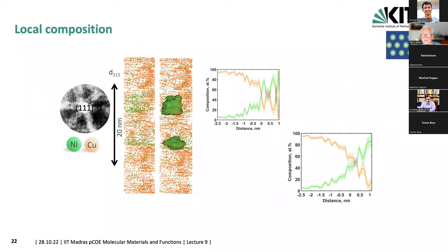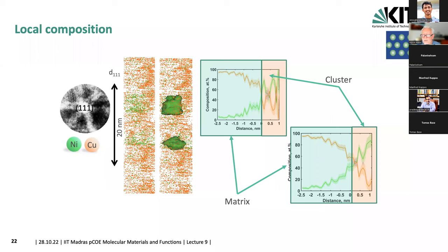So this is good news, because we can prepare a cluster assembled material where the clusters remain intact, even of a system which is completely miscible. So here you see in yellow where the cluster is located and the other one where the matrix is located. So as you follow that green line, you see that there is a transition range between the cluster and the matrix, which corresponds basically to a diffusion profile already, even in the as-prepared material. But there are regions where we have 100% nickel still left in this cluster assembled material.